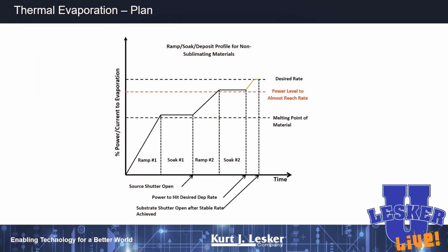Now, we always recommend that you do some kind of a ramp and soak procedure when you're trying to do a thermal or E-beam evaporation. You have an initial ramp and soak up to a temperature hot enough that you can desorb all the water and fingerprints and junk off your system. Maybe you do this with your shutters closed, and maybe a second ramp and soak, maybe with your shutters open, where you're looking at your quartz crystal microbalance and seeing how your deposition rate is increasing, and then a final short little ramp up to the desired rate that you need.